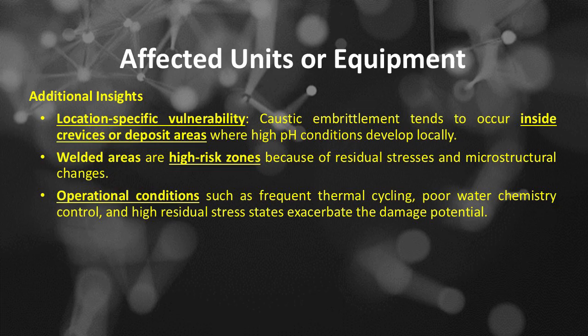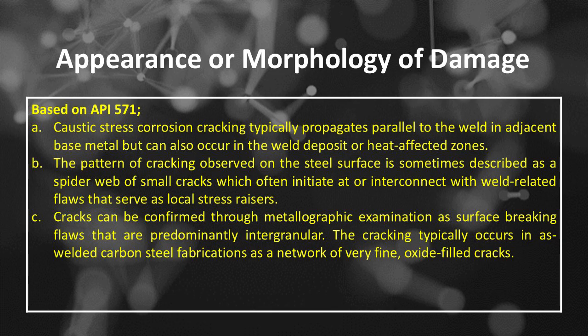Operational conditions such as frequent thermal cycling, poor water chemistry control, and high residual stress states exacerbate the damage potential. Appearance or morphology of caustic stress corrosion cracking or caustic embrittlement, based on API 571. Number A. Caustic stress corrosion cracking typically propagates parallel to the weld and adjacent base metal but can also occur in the weld deposit or heat-affected zones.